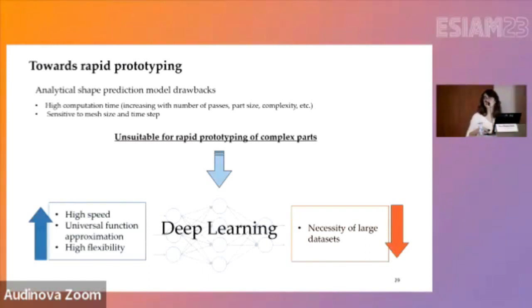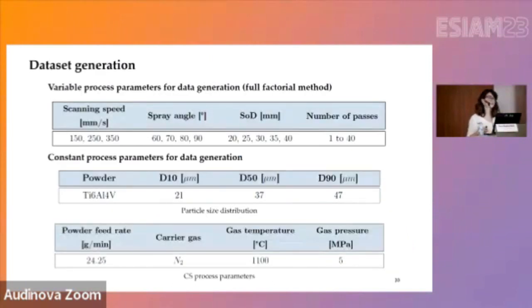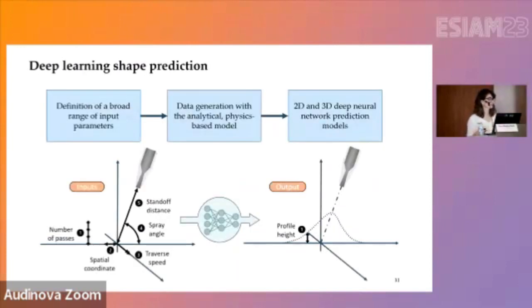So we have very recently started pairing the analytical model that was originally developed in our team with these deep learning approaches. We started with this for Ti-64 with the full factorial method, running the analytical model for a series of parameters in order to create the data set that we need for the deep learning approach. So the parameters that we have started implementing for now are the number of passes, standoff distance, spray angle, traverse speed, and of course parallel tracks.